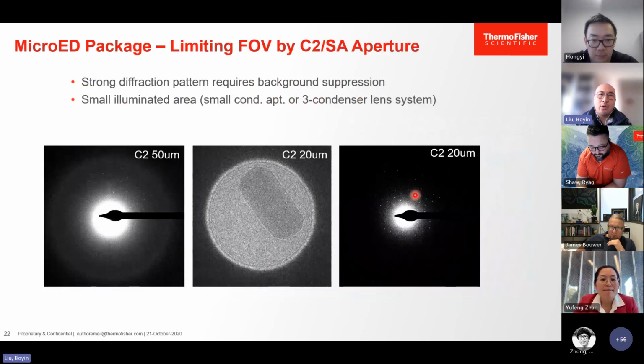This is also part of the MicroED package, the 20 micron C2. When you don't have the package and use the 50 micron C2, you can see there's lots of scattering of the signals here, and you need to add an additional SA aperture to mask this scattering signal. That includes more operation and more alignment. With the 20 micron C2 aperture, you just need the C2 aperture. You get very sharp signals, a very good signal to noise ratio.